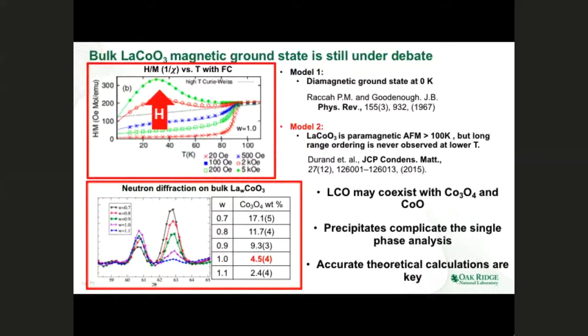But before going into that, there are still other debates. Lanthanum cobaltite is a very complicated material. When we look at bulk lanthanum cobaltite, we again see two different models which can explain its ground state magnetic structure. The first model, going back to even the 60s, says that the ground state should be diamagnetic. The second model, which is a more recent one, relies more on better sample preparation methods and single crystals, and suggests that lanthanum cobaltite should be paramagnetic, with antiferromagnetic order at about 100 K.